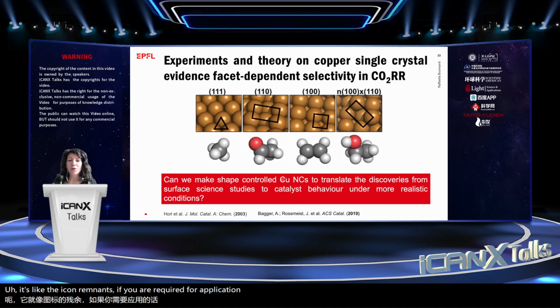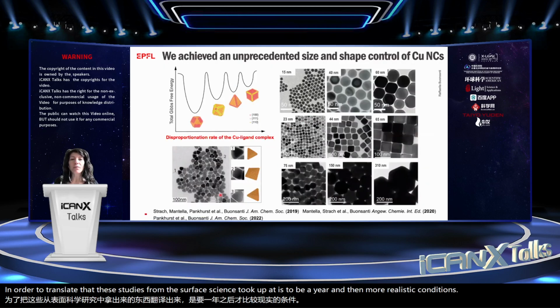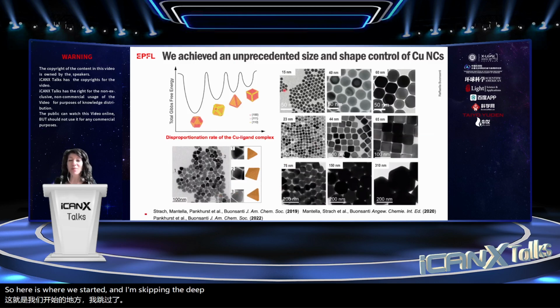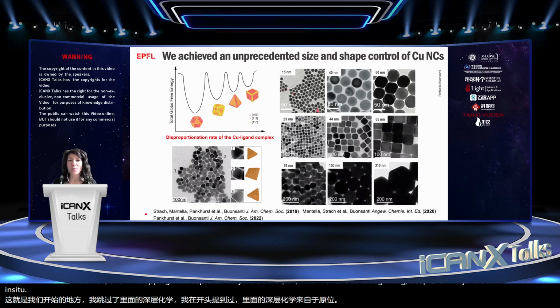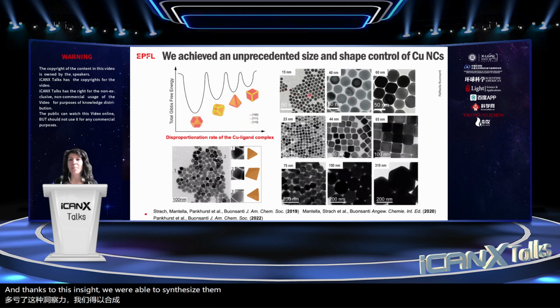required for application. So the first question that my group tried to address was if we could make shape-controlled copper nanocrystals in order to translate these studies from surface science to catalyst behavior under more realistic conditions. So here is where we started, and I'm skipping the deep chemistry insight that I mentioned at the beginning, which came from in situ measurements. Thanks to this insight, we were able to synthesize copper spheres of different sizes, copper cubes of different sizes, and copper octahedra of different sizes, and also tetrahedra that were not synthesized up to that moment. I like to point out that the cubes expose mostly 100 facets on the surface, while the octahedra expose mostly 111 facets, and the spheres have a mixture of both.